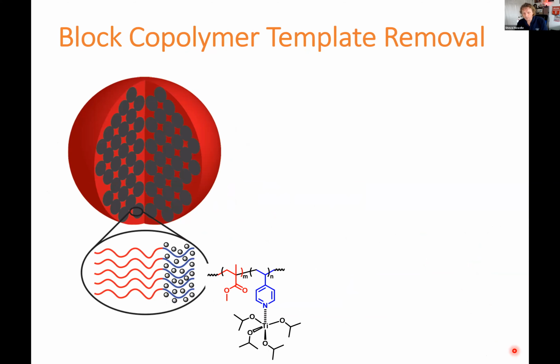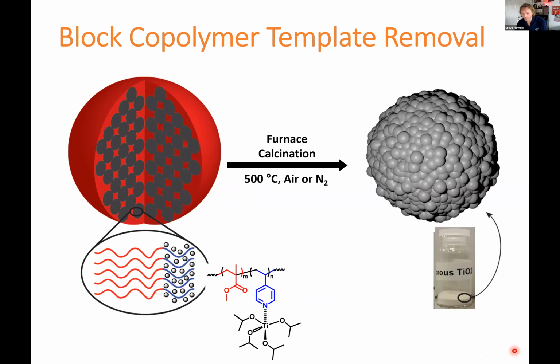Then we remove the template by heating it up. We do this by calcination, and we end up with a structure that is a match templated from the original polymer. But there's now very little carbon, no carbon present at all. It's just all TiO2.